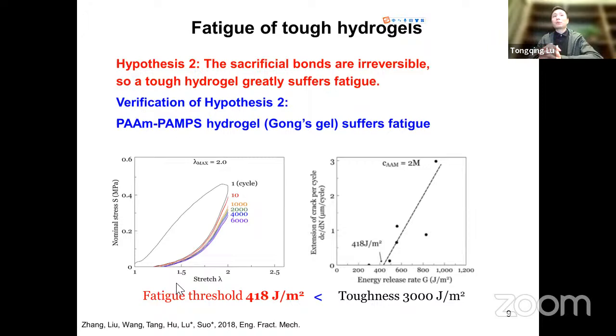So it means we do not particularly study the frequency effect or the viscous effect. But we can see that after many cycles of load, the loading and reloading curves almost coincide, so the hysteresis is very small. When we study fatigue, as we know, for many different materials like metals or composite polymers, when we report, for example, the fatigue threshold or other fatigue properties, you need to fix the frequency. So here we do not study the effect of frequency.